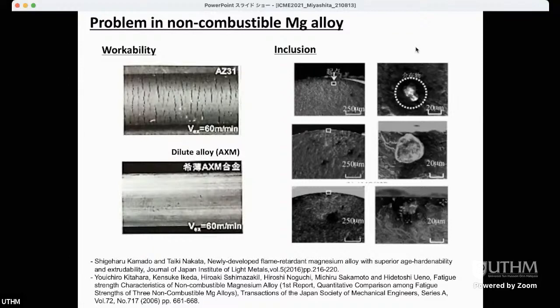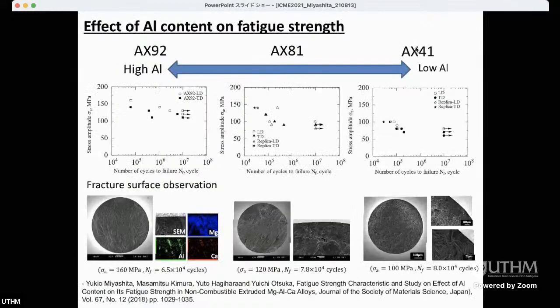I mean that if we increase the aluminum content, mechanical property basically increases, but formability decreases and also inclusion size in some cases increases. So we need to consider the effect of the alloy element. In this case, we carried out fatigue strength tests with 3 different magnesium alloys. As you can see from this figure, if you compare the fatigue strength among the 3 alloys, if the alloy has a high aluminum content, fatigue strength is high. But if aluminum content is low, fatigue strength is low.